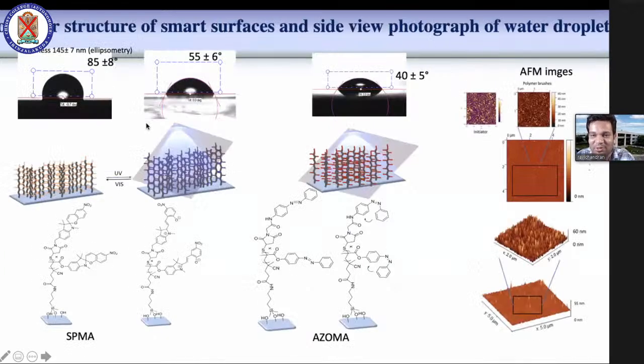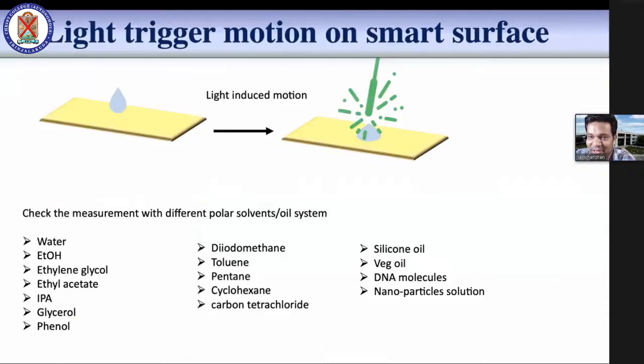The best way to see how it works is to measure the contact angle, from hydrophobic to hydrophilic. So here, before excitation, it is hydrophobic. After excitation, it goes to hydrophilic, which is 85 to 55 degrees. And in the case of azobenzene, you can also go from the hydrophobic to the hydrophilic region by measuring the contact angle.